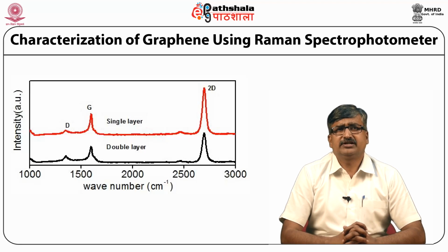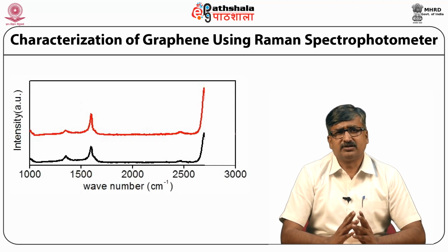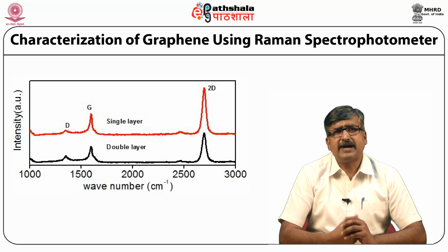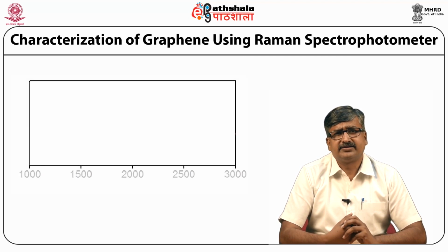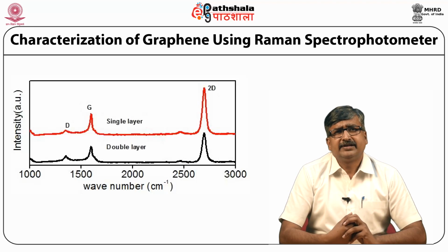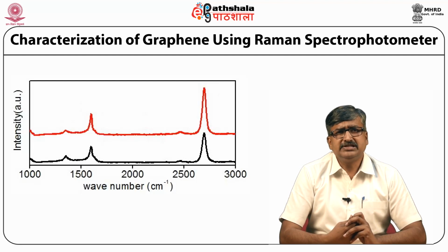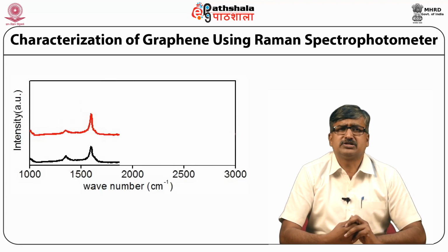The spectra exhibit a relatively simple structure characterized by two principal bands, designated the G and 2D bands. A third band, the D band, may be apparent in graphene when defects within the carbon lattice are present. These differences, although they appear subtle, supply very important information when scrutinized closely.